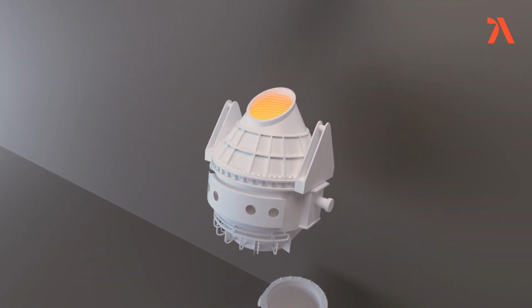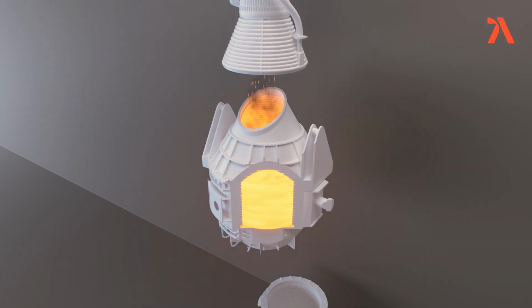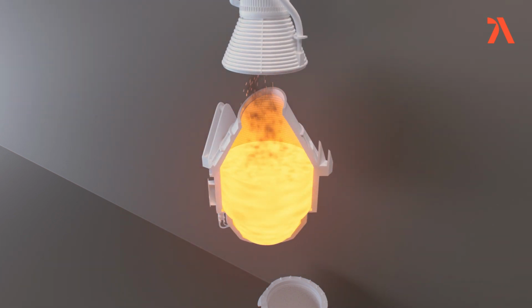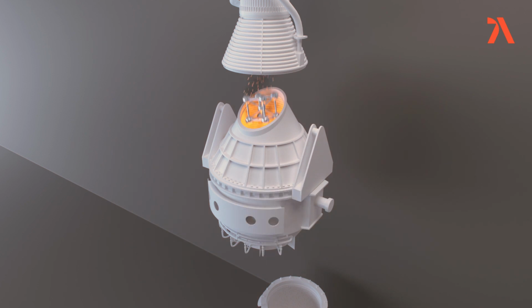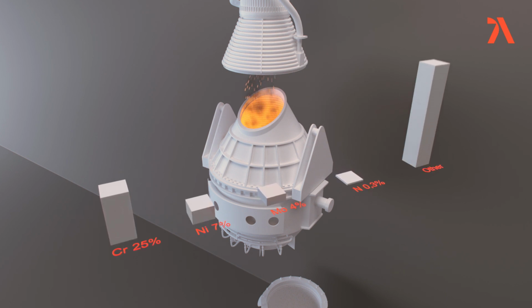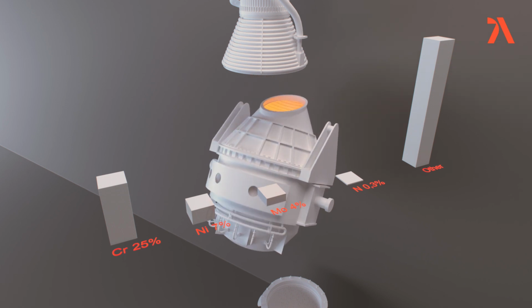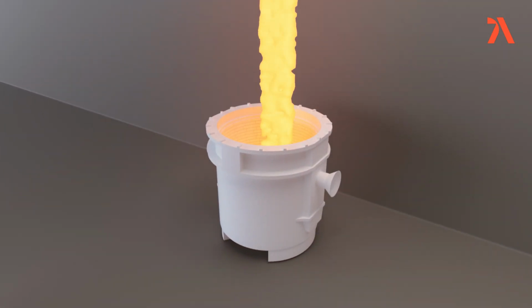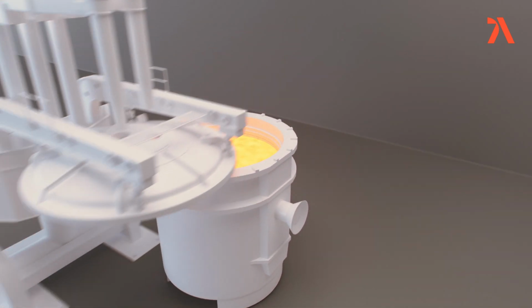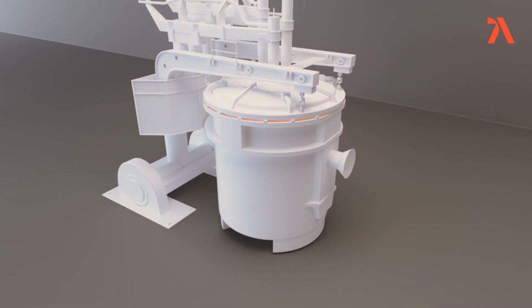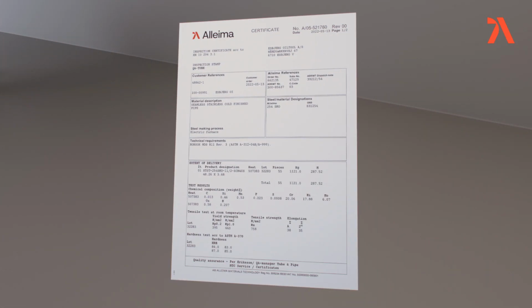Exhaust gases from the furnaces and AOD processes are filtered to cut pollution, and the dust extracted is further processed for metal recovery. The chemical composition of the melt is closely monitored throughout the process to meet our own demanding standards. We make continuous analysis to guarantee the correct steel grade and ensure traceability and consistency between the batches. The melt is transferred to a ladle furnace for fine-tuning of temperature and composition. The results are entered in a form that accompanies each batch at every stage of the process.